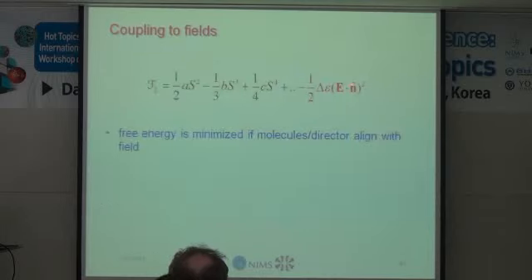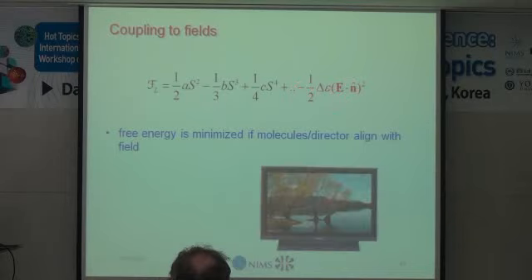And so now this additional term is important, because if delta epsilon is positive, as it is for most rod-like molecules, this means that to minimize the free energy, N wants to be parallel to the electric field. So the molecules like to align with the electric field, and this is then the mechanism that essentially all displays are predicated on. You align the molecules by applying an electric field.